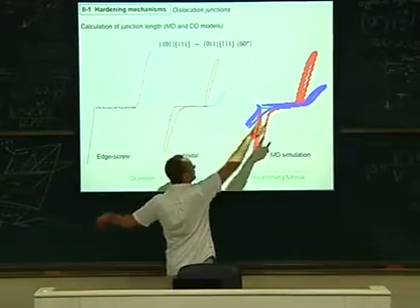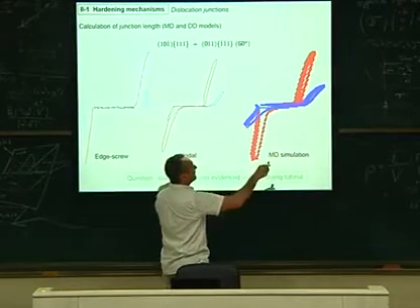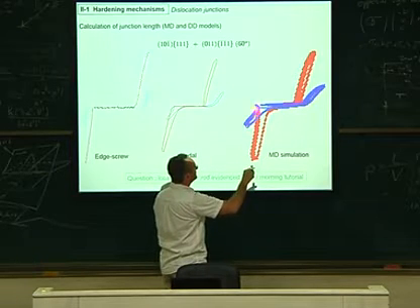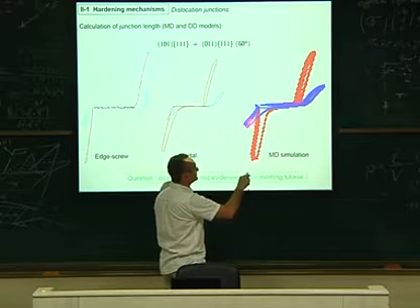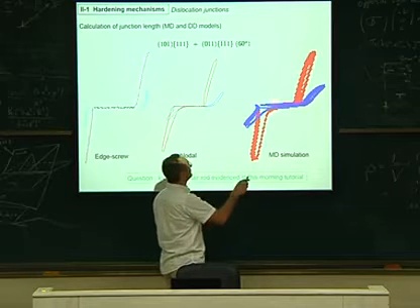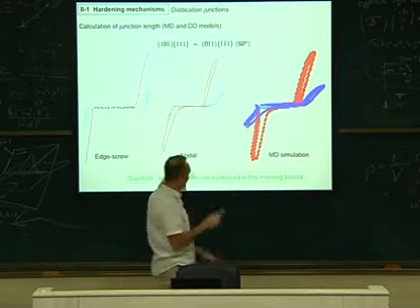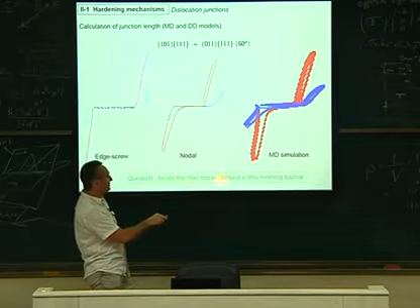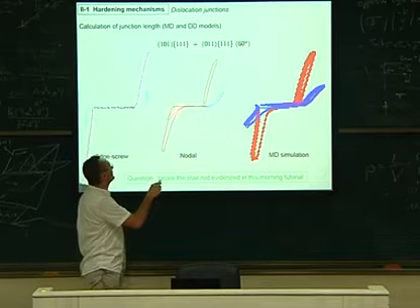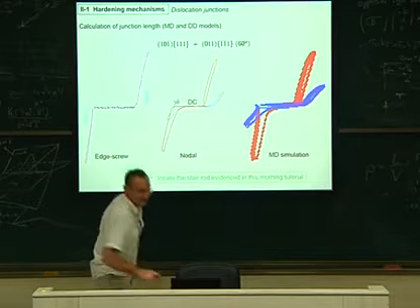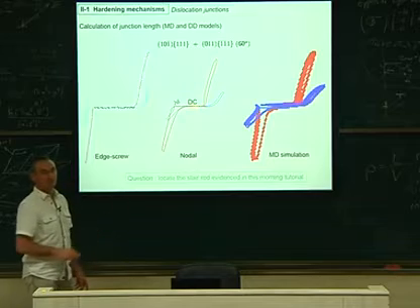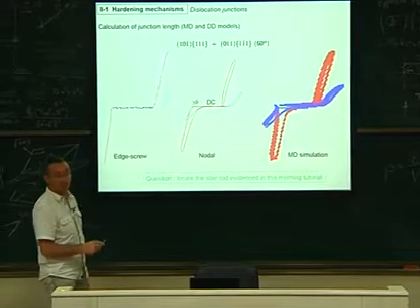Initially you had the two arms, the blue and the red one, pinned at the extremity, and you let them relax. And you can see that here you have a partial splitting. This is a stacking fault here. Here there is something, you have to tell me what it is. It is? Stair-rod, yes, I had a question. Locate the stair-rod evidence from this morning's tutorial. It is here. This is the stair-rod, yes indeed. This is my stair-rod, okay? The stair-rod is here, and this is the pure Lomer-Cottrell junction, as we saw this morning.